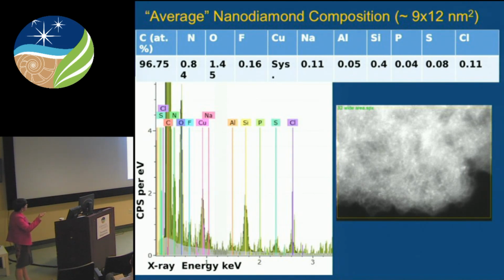Now, that's actually a really slow way to do it. You may want to get the average or bulk composition of the nanodiamond residue, and by bulk, in this case, I mean an area of 9 nanometers by 12 nanometers. And we can see that these residues contain a lot of different impurities.